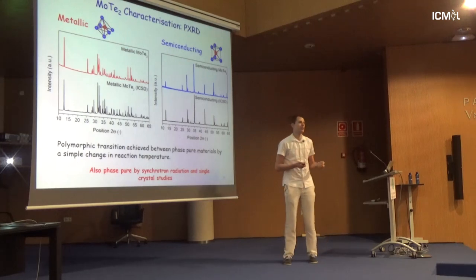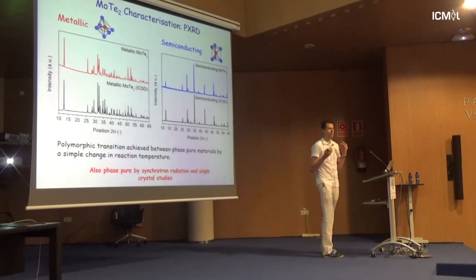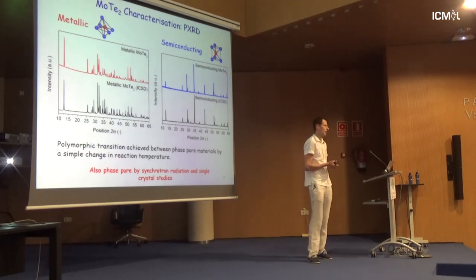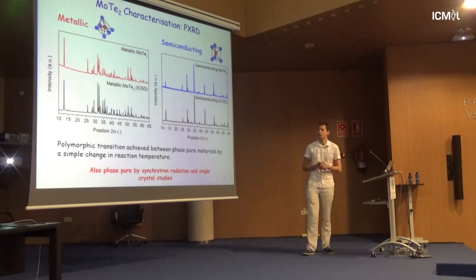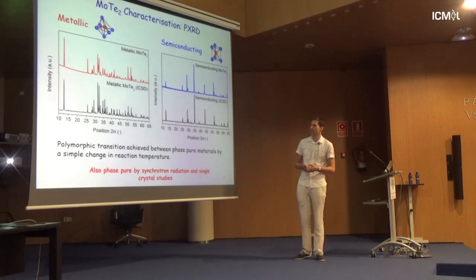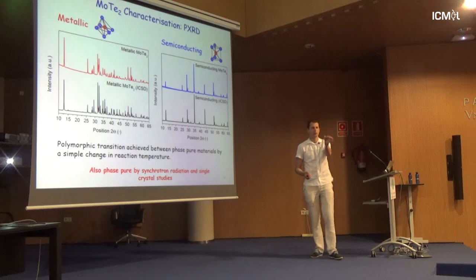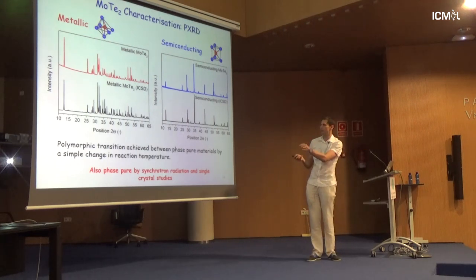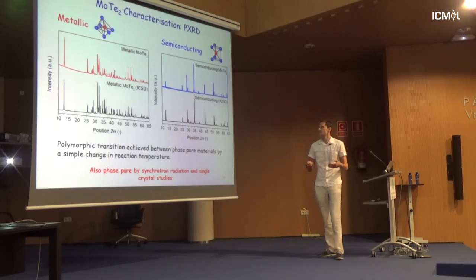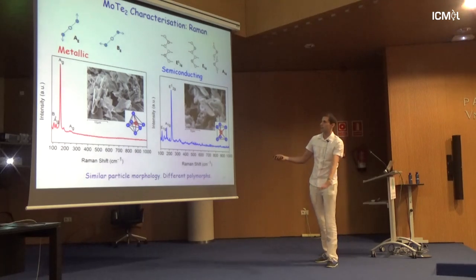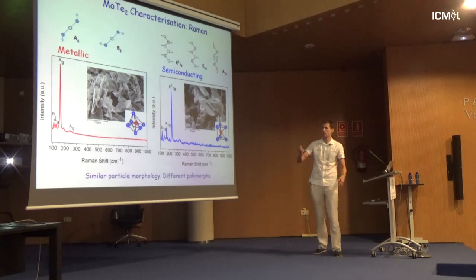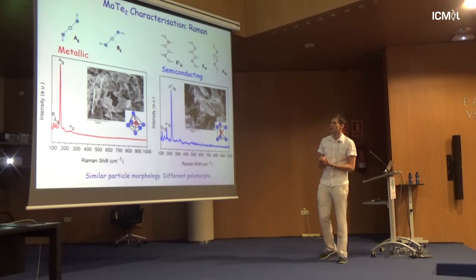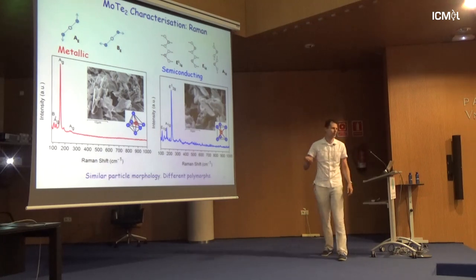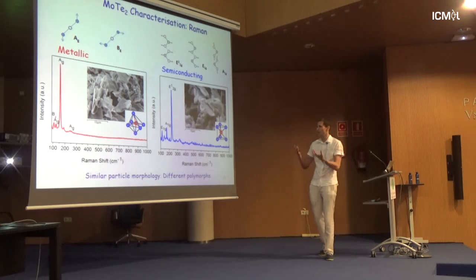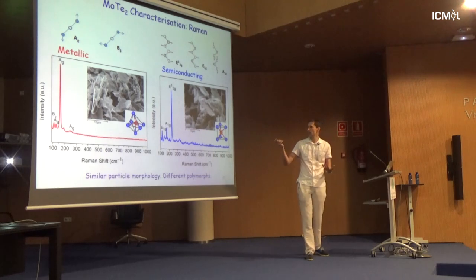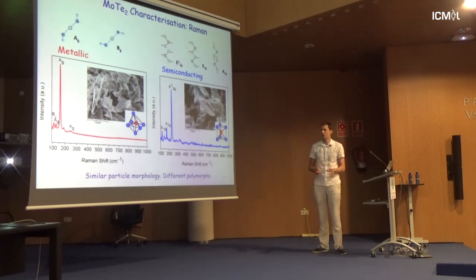And of course, the biggest challenge with a catalyst is that you operate in extremely corrosive conditions. It's very important nowadays to demonstrate that we actually survive. And what we normally do, we have the electrode and we can do in situ characterization, so it's the scan, and demonstrate before and after, and it just shows. But this is just an example of metallic and semiconducting, so a little bit of microstructure, so the microstructure practically retained. There are a little bit more blurry images. The reason why they're more blurry is because it's a semiconducting phase. So your SEM sees it as less conductive, so we didn't cover this with gold on purpose. And this was again measured directly on the electrode.